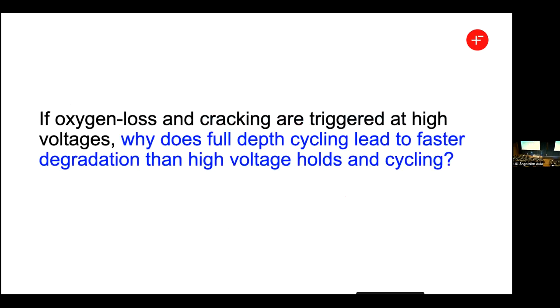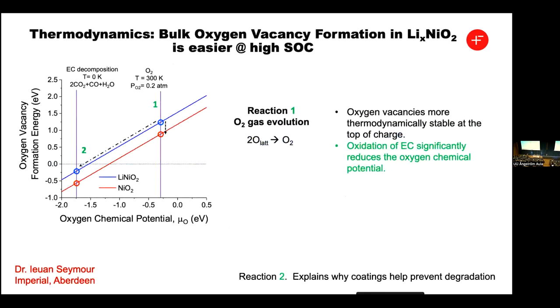So I then want to return back to this question. Why does a full cycle trigger so much more aging than just the hold at high voltages when you get a lot of degradation? To look at this, a former postdoc, Yian Seymour, who was at Imperial and is now at Aberdeen, looked at the thermodynamics associated with oxygen loss from the structures. And what he showed was that there are two mechanisms. Reaction one is a direct oxygen evolution reaction. Reaction two is that coupling between an EC oxidation and an oxygen loss.